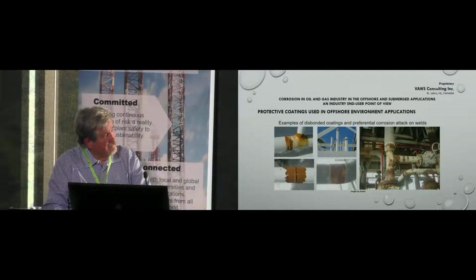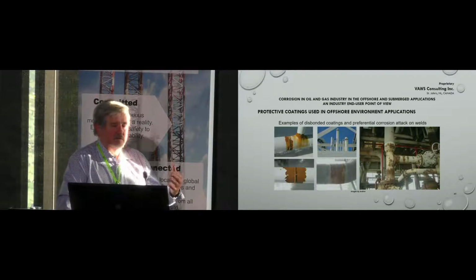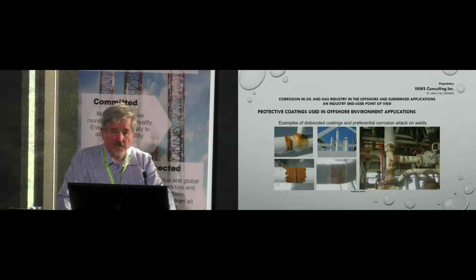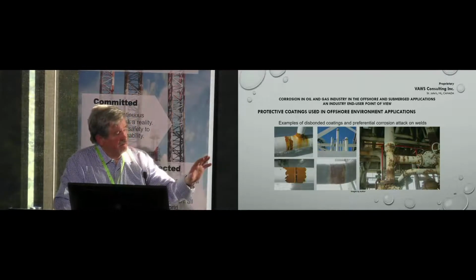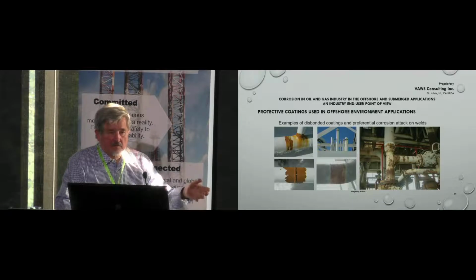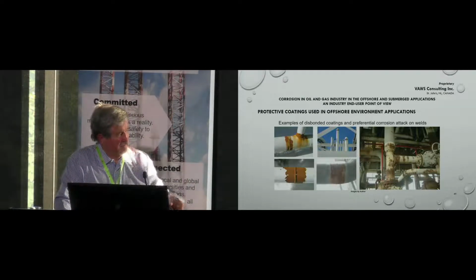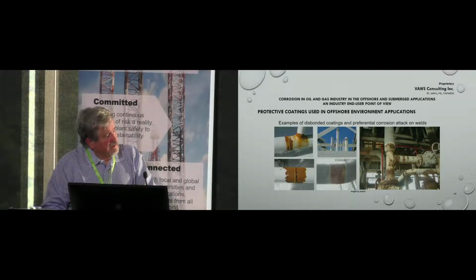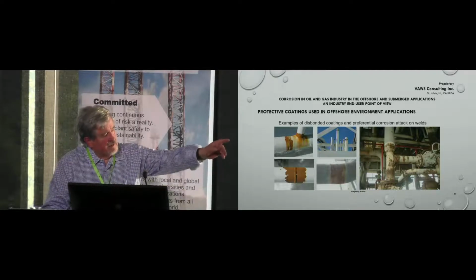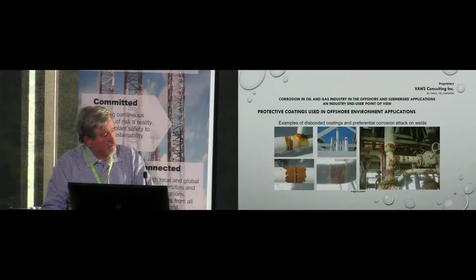Here's an example of welds in one of the operations we had. You can see that when you have corrosion around those welds, you also generate hydrogen, of course. And under the paint, no matter how good that paint was, you will develop bubbles, and eventually the paint will fail. And you can see that it progresses from that part on. And it can look really ugly real quick. On the last picture on the right, I don't know if you can see it where you are sitting, there are grooves around the welds on both sides. What you have to do is to reweld those things again and try to do it better next time.